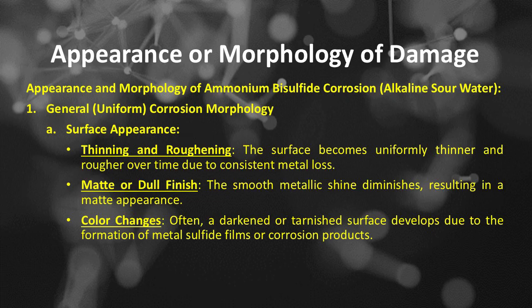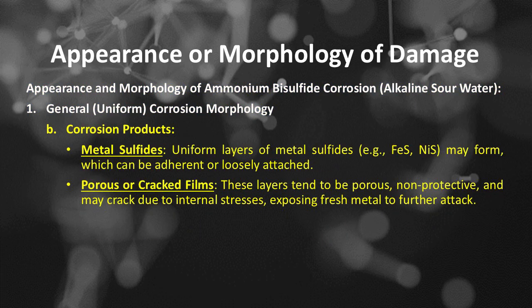The surface appearance of general or uniform corrosion includes thinning and roughening. The surface becomes uniformly thinner and rougher over time due to consistent metal loss. Matte or dull finish: the smooth metallic shine diminishes, resulting in a matte appearance. Color changes: often, a darkened or tarnished surface develops due to the formation of metal sulfide films or corrosion products. Corrosion products of general or uniform corrosion include metal sulfides.